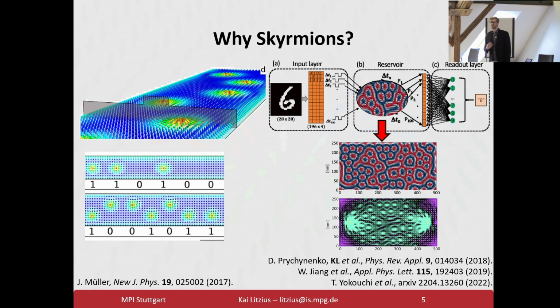And this kind of proposal has both memory properties as well as synaptic properties in one go. For example, when you shift them just a little bit, they will relax back to the original position. So this is a short-term memory effect. While if you shift them quite a lot, it's a long-term memory effect, because you permanently alter the magnetic textures inside of the reservoir. So this is an effect where you could use the 2D properties in a more detailed way. But for this, you need to understand properly what the skyrmion texture does under specific conditions, and you need to know how to create certain states in the system.